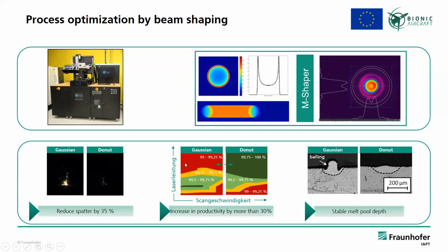For instance, here with higher laser power in the Gaussian field, you will have the balling effect and therefore no more secure production with regards to density. In the donut, you will have still a smooth and stable melt pool, allowing you to work in this range of speed. So it allows higher productivity and at the same time a more stable melt pool instead of the balling effect that we want to eliminate, of course. So as you see, some potential in the process to optimize performance and cost.